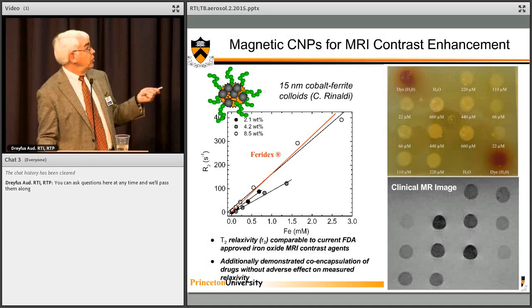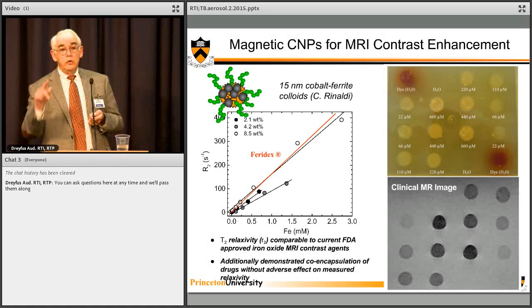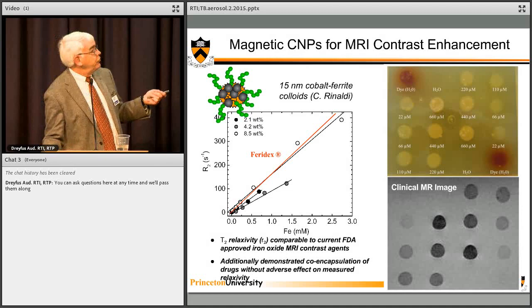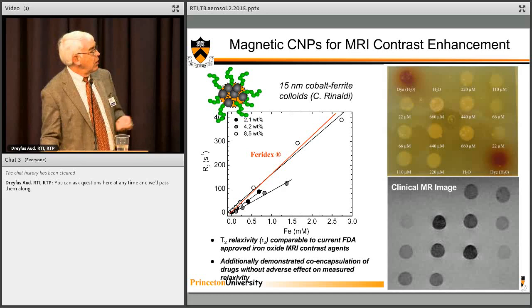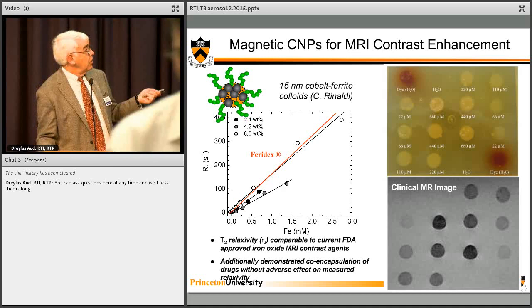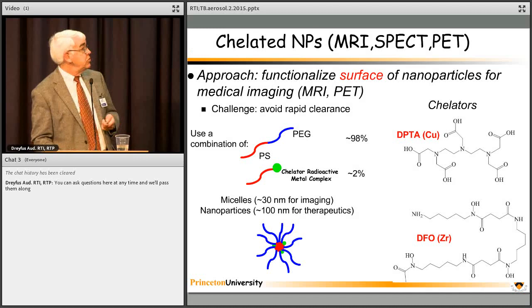These are superparamagnetic oxide ones. You coat them with hydrophobic materials, precipitate them, and now we've made an MRI imaging agent. This shows a gelatin well, and here are different concentrations, and you get very good MRI signals. This is the relaxivity, this is iron concentration, and these particles are in the same relaxivity spectrum as commercial materials, which are sold as imaging agents.